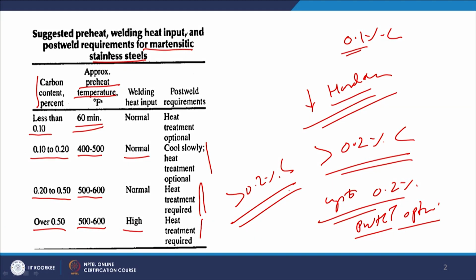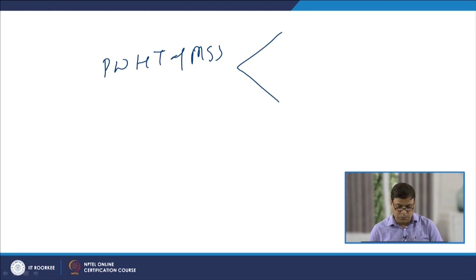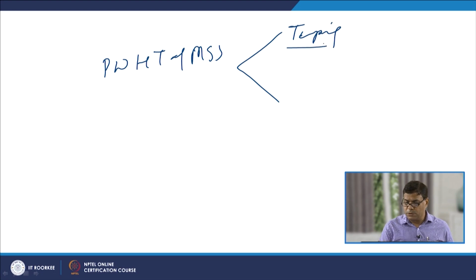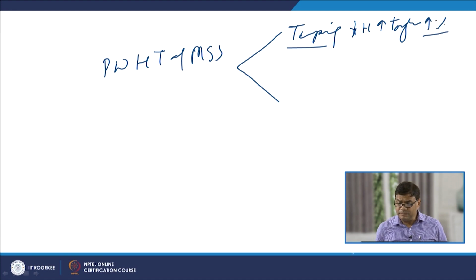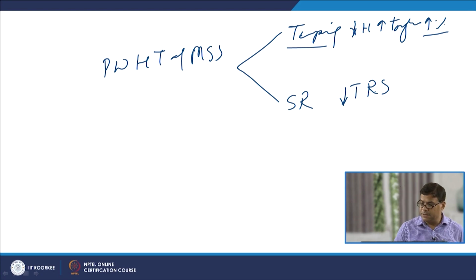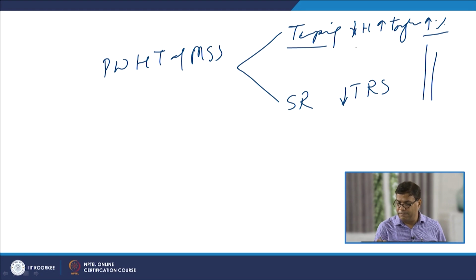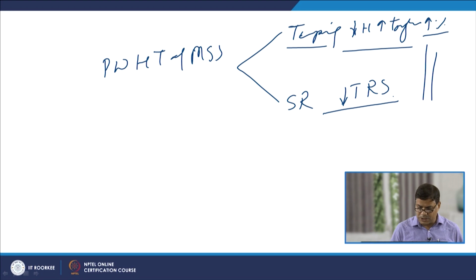So, what are the purposes of the post weld heat treatment and the kinds of post weld heat treatments which are carried out? Post weld heat treatment of the martensitic stainless steels. There are two broad categories of post weld heat treatment. One is used for tempering purpose. Tempering will reduce the hardness, increase the toughness of the weld joint, and improve the percentage elongation and the ability to take up impact load. On the other hand, stress relieving heat treatment is also carried out in order to lower the tensile residual stresses if they have developed. So, these are basically the two purposes of performing the heat treatment: improving the toughness, reducing the hardness, and relieving the residual stresses.